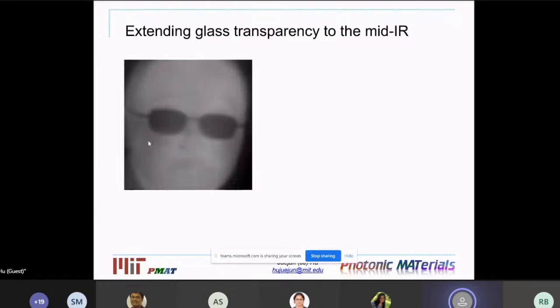So to show that, I'm showing you here an image, okay? Once I presented this image to the students in my class and asked them to guess who this person is, the answer I got from the class is that this is Morpheus from the movie Matrix. Now, obviously, I know that I'm not looking that good. This is actually my infrared selfie I took using an infrared focal plane array camera. Now, what I want you to focus your attention on is my glasses here. These glasses made of oxide glasses are perfectly transparent in the visible, but you see that they actually turn dark in the infrared. So they strongly absorb the infrared light.